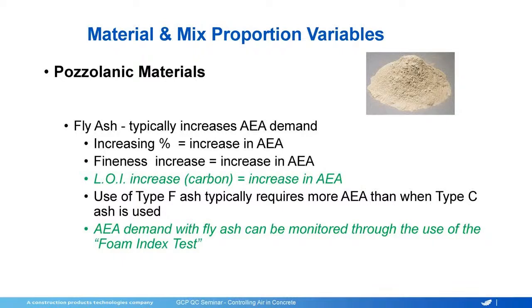The type F ashes do tend to have a higher AEA demand, and that's typically because they have a higher LOI for the most part than the type Cs. And you can use the foam index test as a quality tool to check your incoming fly ash samples. It's a very easy test to run, doesn't require a lot of training. And if anybody's interested in that, you could email me at any time and I can send you how to do that. But it is something that's doable.